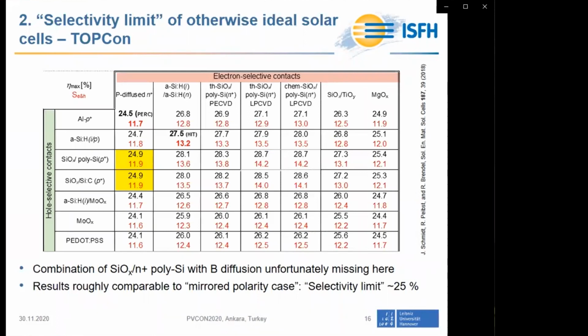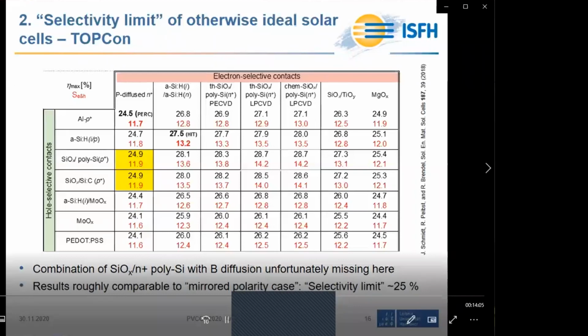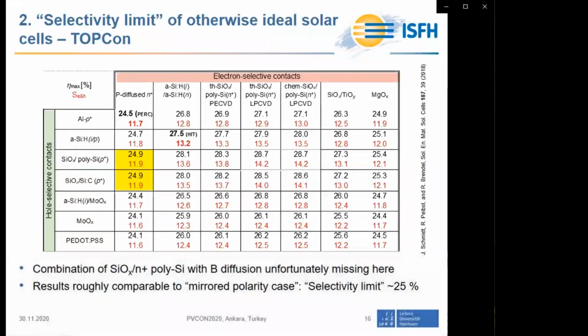The most prominent cell structure, including such a combination, is the so-called TOPCon cell structure, which combines a conventional diffused boron frontside emitter with a polysilicon oxide electron collecting junction on the rear. Unfortunately, we have missed the boron emitter here in the screening. Nevertheless, we think that the results for this combination are pretty much comparable to the results for the mirrored polarity case.